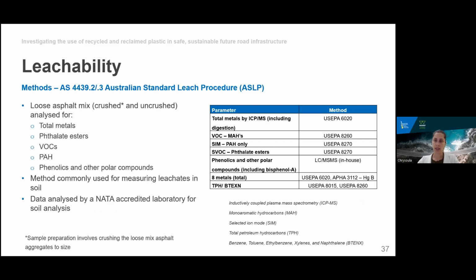We also tried to assess the loose mix asphalt for leachates using the Australian standard leach procedure. This method is commonly used to measure leachates in soil. We tried this method by both crushing our loose asphalt mix to size, where I will refer to this as crushed, and by sieving the loose asphalt mix to include only those of acceptable size, avoiding crushing. I will refer to those as uncrushed. We then assessed for metals, phthalate esters, VOCs, PAHs, phenolics, and other polar compounds.